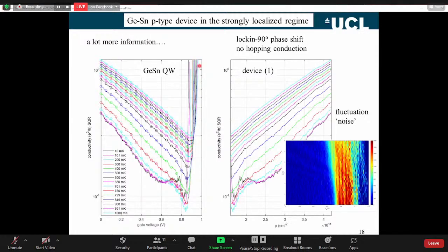10^11 carrier density. We can plot this out as a function of carrier density. These are all at constant temperatures. Conductance down, the contacts start to get this fluctuation noise. But then at very, very low carriers, we lose the device. It becomes resistive.